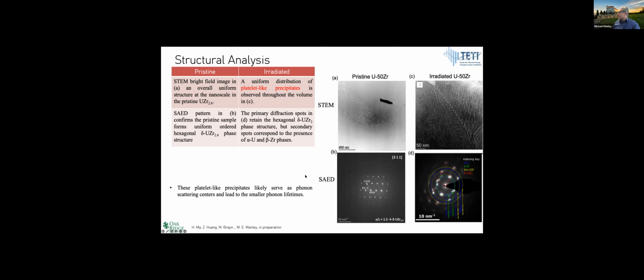And when we do the fits to the phonons, we see little extra features in there that we have to fit and just sort of identify. Especially the alpha zirconium, which is actually also hexagonal, so they kind of sit right under it. But yeah, it's a complicated problem.